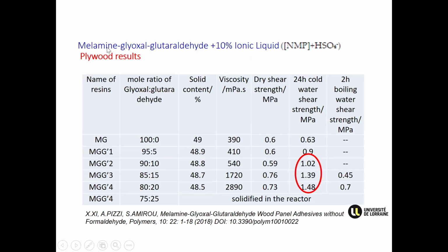Then we developed melamine glyoxal glutaraldehyde with 10% ionic liquid, and you can see that with the two aldehydes you actually got a value of 24-hour cold water shear strength that is actually very good. There's no problem from that point of view.